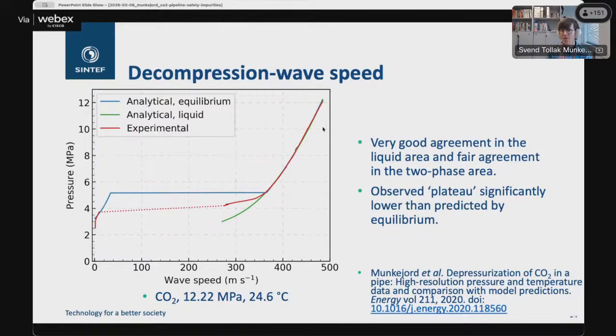So if we concentrate first on the right-hand side, the decompression starts here at 12 megapascal, then it goes downwards like this. You can see here there is good agreement between experiment and calculation. We used, by the way, for pure CO2, the Span-Wagner equation of state here. At this point, interesting stuff is happening.